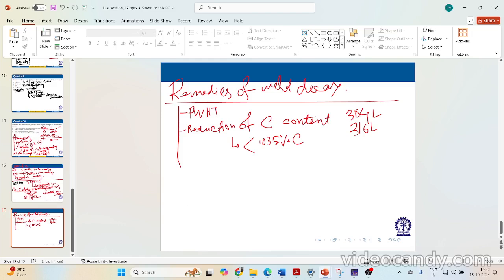What else you can do? You can add some strong carbide formers so that the carbon is tied up. What are those? Elements like titanium and niobium have greater affinity for carbon than chromium, so they form carbides more easily than chromium.